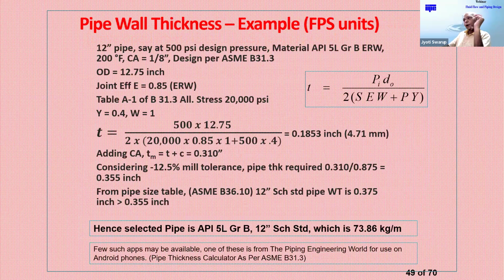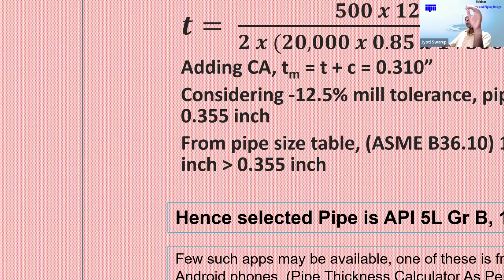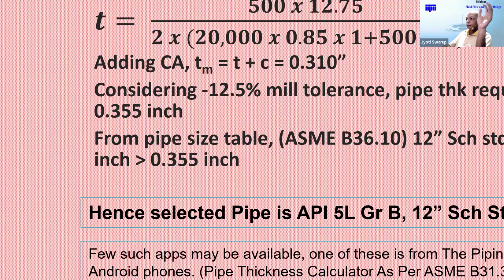Now I have given an example here for a 12-inch pipe, 500 psi design pressure, material API 5L grade B ERW, electric resistance welded pipe, 200 degree F, corrosion allowance 1/8 inch, designed as per B31.3. So you can calculate the thickness, add to it the corrosion allowance, and also consider 12.5% mill tolerance. So you calculate the required thickness 0.355 inch, but from the table of the sizing of the pipe, from 0.355 inch, you see which is the pipe thickness available next to it.